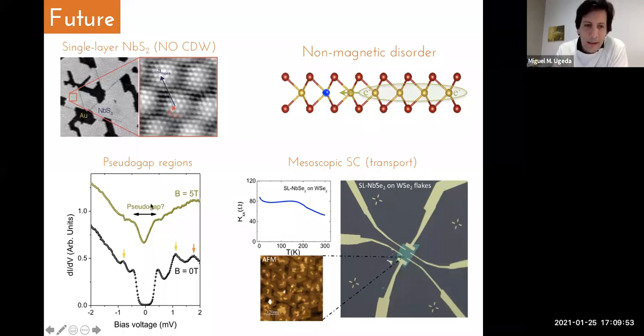We would like to study something that we recently became aware of and don't fully understand, which is the V shape in the density of states well above the critical temperature. So when the system is not superconducting, we still see these deep features that make us believe that probably these are pseudogaps, which could be in line with unconventional properties of this material.